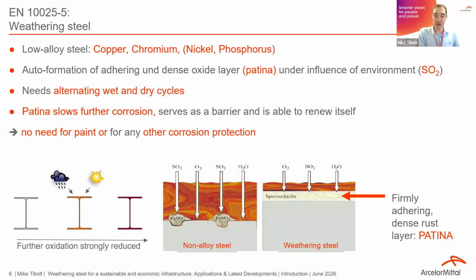And this leads to an auto formation of an adhering and dense oxide layer at its surface, which is called the patina, and this under the influence of the environment, especially under the sulfur dioxide. So that the patina can form, we would need alternating wet and dry cycles. And this patina that forms will slow the corrosion rate. So it serves as a barrier, and it is able also to renew itself whenever it gets damaged. And because this patina forms itself, there is no need to paint or to apply any other corrosion protection on the steel.